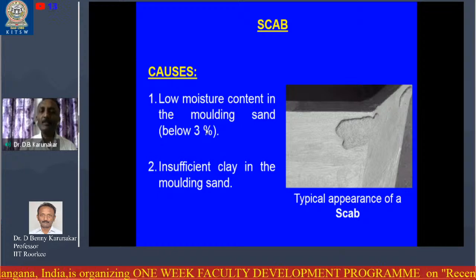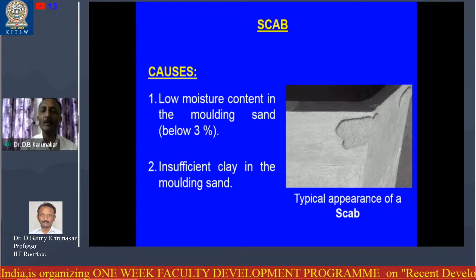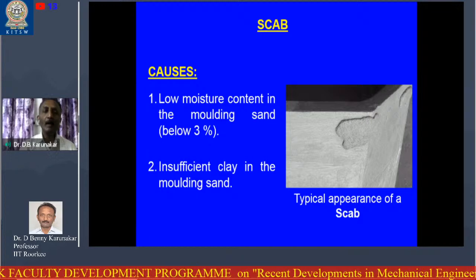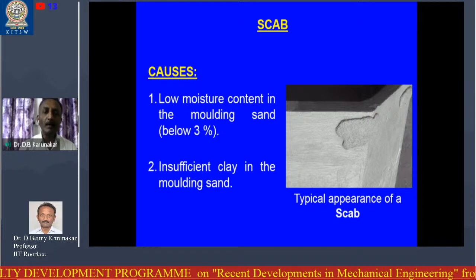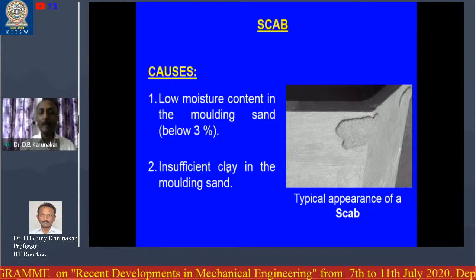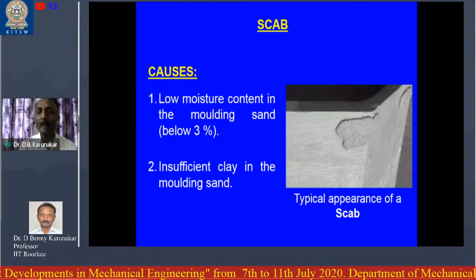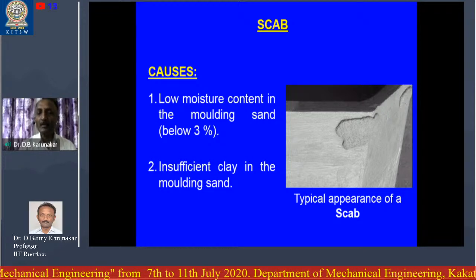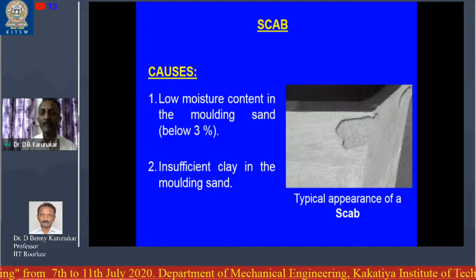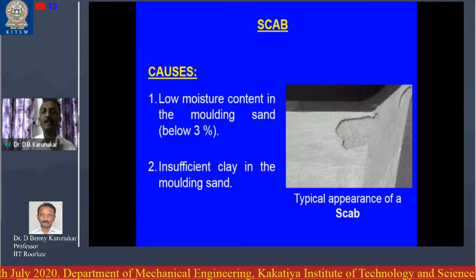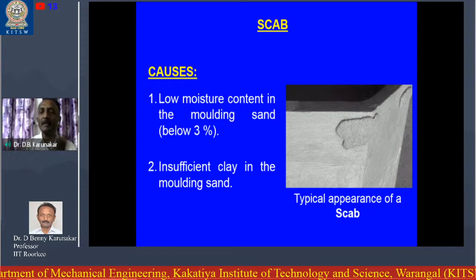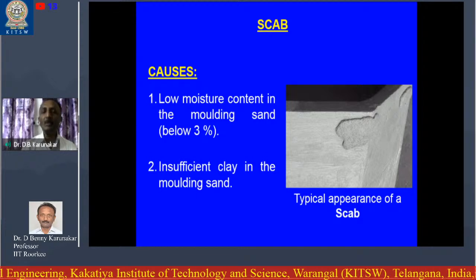So the molding sand was loosely bound. Another reason could be low clay content, insufficient clay content. We have to add sufficient moisture and clay content so that when we mix the molding sand, the particles stick to each other very tightly. There should not be any loose contact.